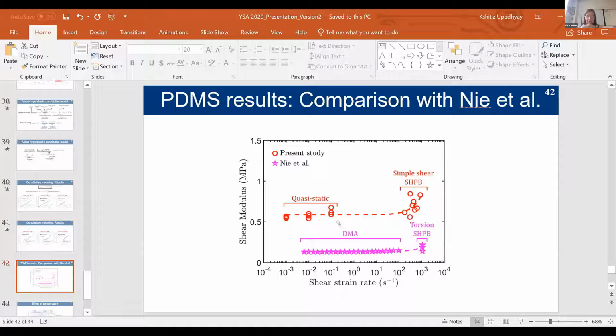Have you done any statistical analysis to see whether between your 10 to the minus 3 strain rate and your 10 to the minus 1, that is or isn't an increase? Definitely, yeah. I have done a statistical analysis, and this paper has actually been published, and there is a statistically significant increase in the modulus between the quasi-static and the dynamic strain rate. I was meaning over the 3 quasi-static, which is a factor of 100 difference, isn't it? There is no statistically significant increase in modulus within the quasi-static regime. Okay, thank you.